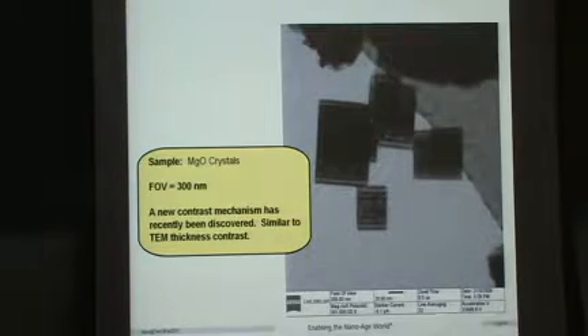We also, when we had that detector, found something we weren't expecting at all. I have made the claims that wavelength isn't important. We're massive enough so the wavelength is quite small, small numbers of picometers. But we saw something that is a wavelength effect. We saw a diffraction type contrast mechanism. These are magnesium oxide crystals. This bar here is 20 nanometers, so it's very high magnification indeed.